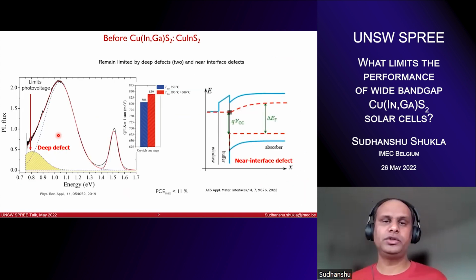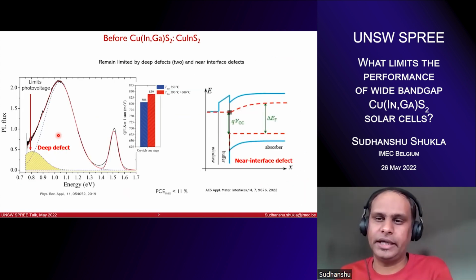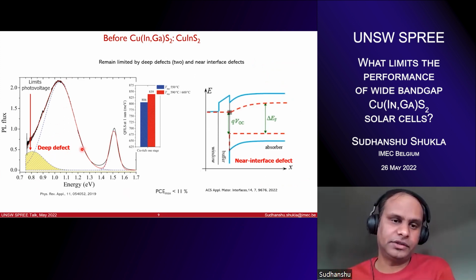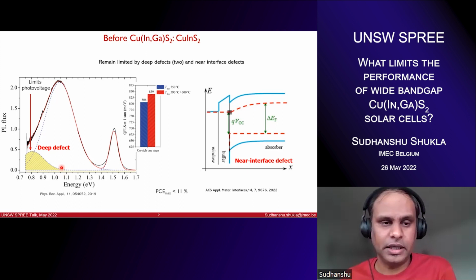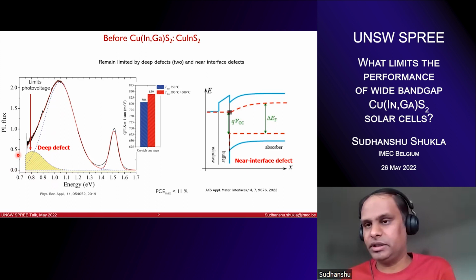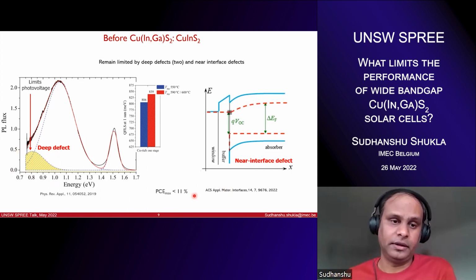So now, before moving on to the CIGS, let's talk about CIS briefly. What we noticed previously is that if you make pure copper indium disulfide, high quality absorbers, you do get these signatures of the deep defects. This is the PL that you get close to the band edge, and this deep broad band that you see at the lower energies corresponds to the deep defects. If you look carefully and deconvolute it, you get two deep defects actually, one close to 1 eV and the other close to 0.8 eV. And this 0.8 eV defect actually limits the photovoltage in the case of CIS.